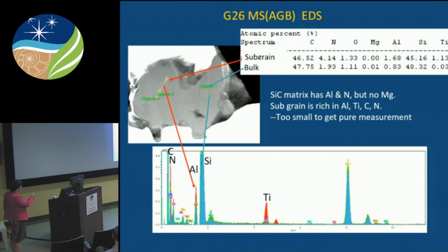When we look at the composition of this grain, so now this is a high-angle annular dark-field image, so the contrast here depends on atomic number. The bright stuff is the underlying gold substrate and an overlayer of platinum deposit in the FIB. This medium gray is all the silicon carbide, and the bright things inside the silicon carbide are subgrains. So this large one here corresponds to the red spectrum down here, so you can see it's rich in titanium, rich in aluminum, and rich in nitrogen compared to the bulk matrix. This is approximately a 100 nanometer area right there, so the whole grain is a few hundred nanometers across.